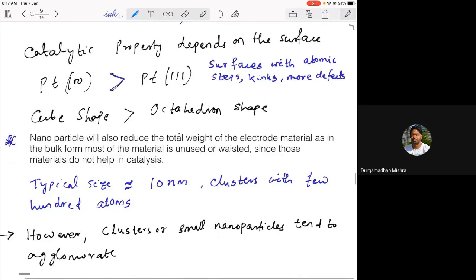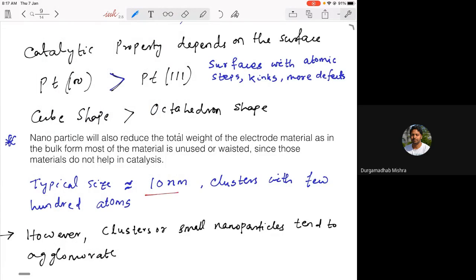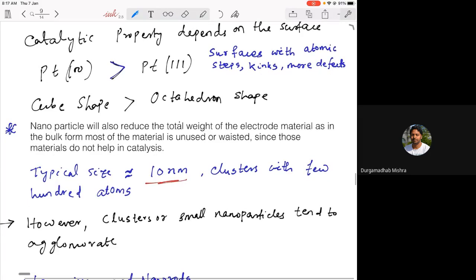The typical size is around 5 to 10 nanometers. But another problem with using these nanoparticles is that since they are so small and reactive, sometimes you need to passivate them. Otherwise, these clusters will agglomerate. Since the surfaces are highly reactive, they always try to minimize the surface energy, and therefore they will agglomerate, which is undesirable.